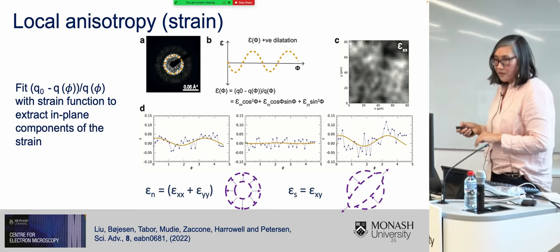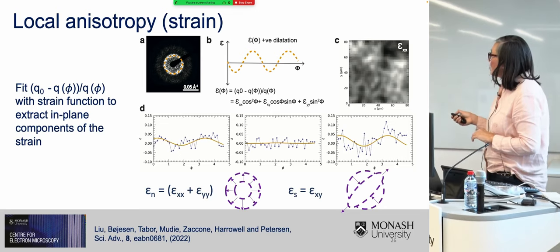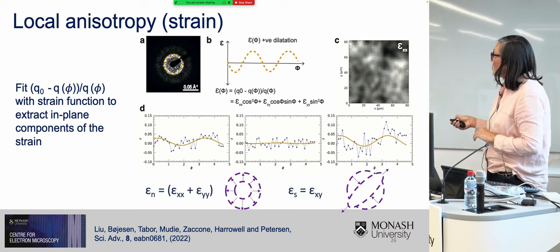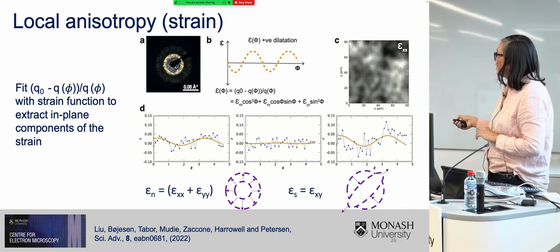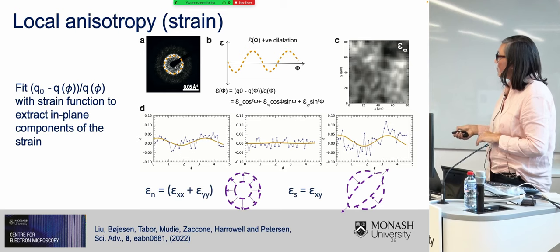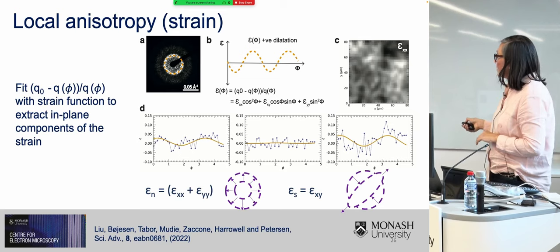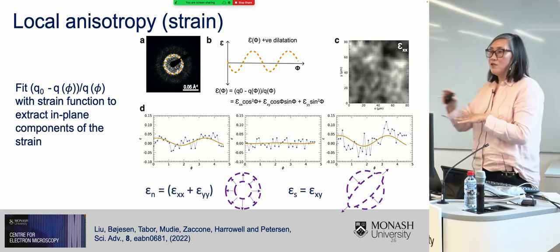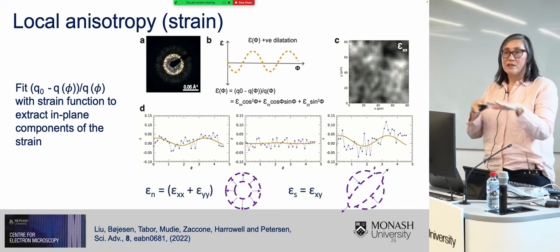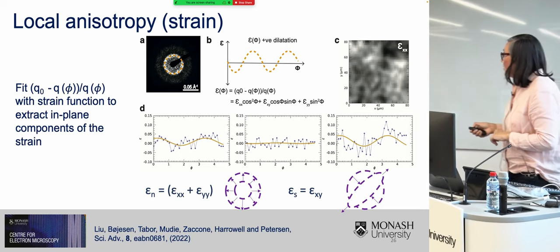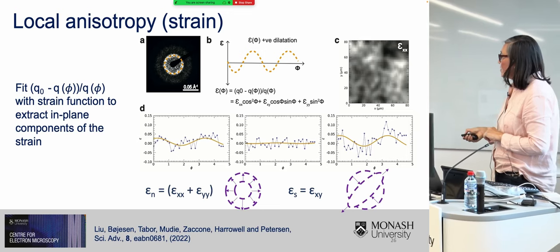And to calculate the local anisotropy or strain, I looked at the position of this first main diffracted peak, and I fitted that position with a strain function, which is given here. And so here are some examples of data that I fitted. And this gives you the in-plane components of the strain tensor. And from these, I extracted other parameters.